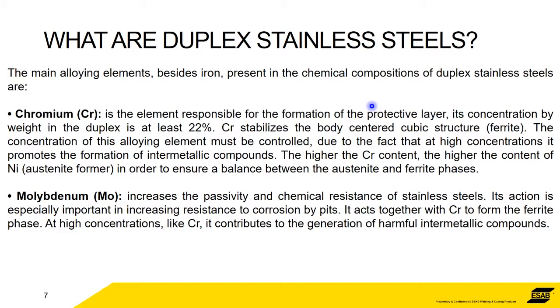Chromium in there is what makes a stainless steel stainless. Anything above 12% chromium generates a chrome oxide layer on the surface. Chrome oxide is very, very resistant to corrosion. But what chrome also does is it stabilizes the ferrite. So in order to get a good balance between the ferrite and the austenite, the content of chrome has got to be balanced with the nickel.